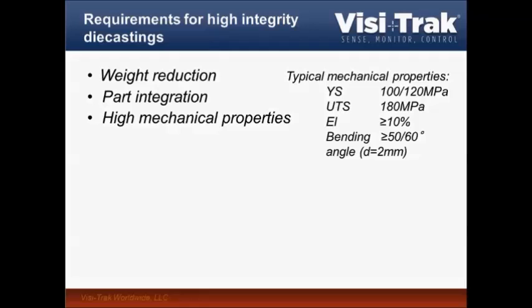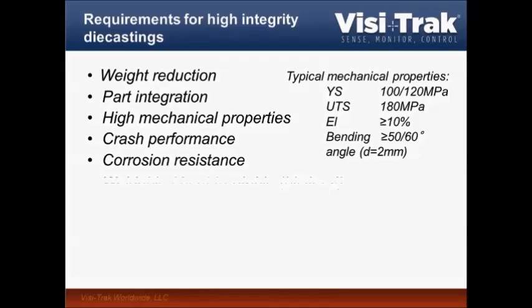Now, of course, we all know that crash behavior in a high-speed impact can't really be measured with a very low-speed tensile test. So therefore, at least a certain bending test, which is very common with sheet applications, is typically used here, but ideally OEMs do real crash test with these parts. So crash performance is of course a big requirement.